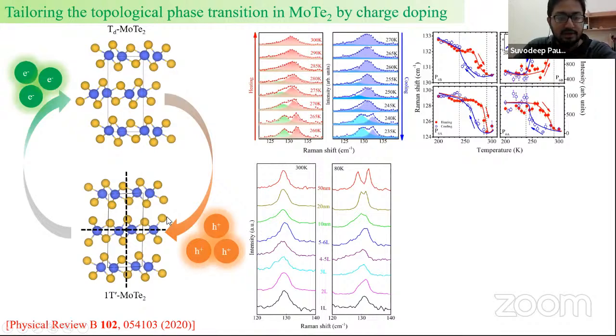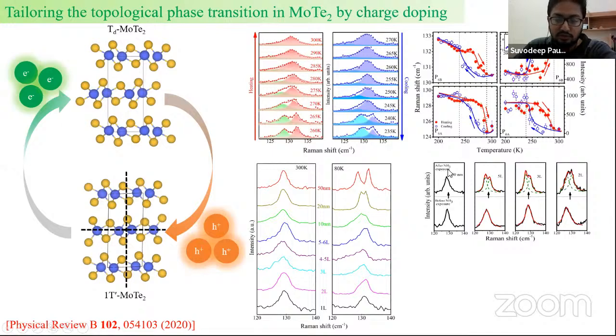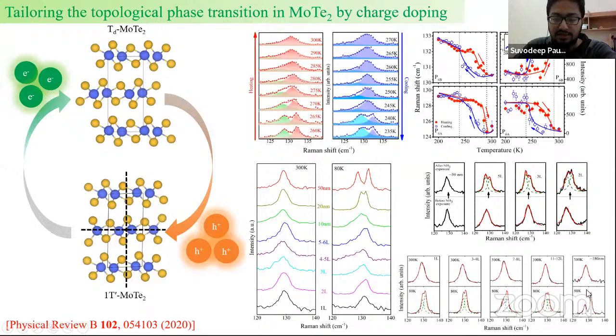Now we see that on electron doping these very thin flakes, by exposing them to ammonia vapor, we get back the Td phase. So this tells us that electron doping can again stabilize the Td phase. Further, when we continue our studies with the rhenium doped sample, which is again rich in electrons, we see the Td phase appear at low temperatures. So this kind of proves that we can interchangeably stabilize either of the two phases by proper electron or hole doping. And further details of this work can be found in this paper.